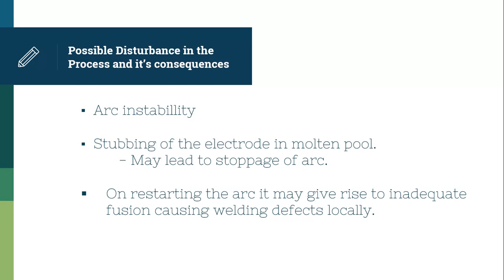Possible disturbance in the process and its consequences. Arc instability. Stubbing of the electrode in the molten pool may lead to stoppage of the arc. On restarting the arc, it may give rise to inadequate fusion causing welding defects locally.